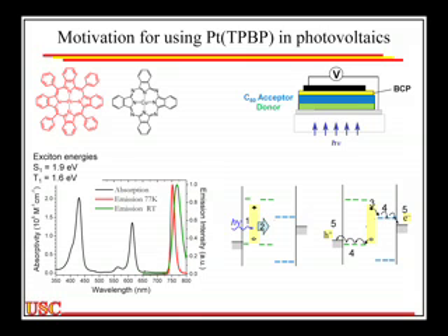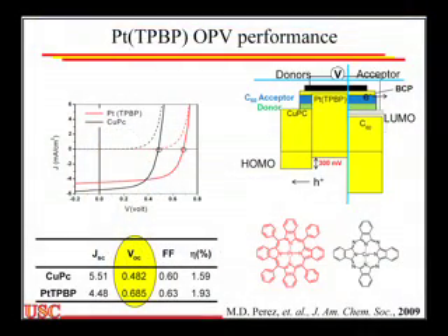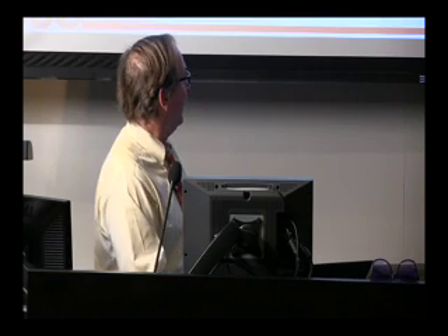The other problems that come up are the carrier conductivity must be high. This is something organics are terrible at, and that impacts the fill factor, so how steep or how much like a hockey stick the curve looks has to do with the conductivity. And we typically solve this by keeping the films thin, but remember, if I keep the films thin, I don't get much light collection, so that's a bit of a problem. And the open circuit voltages are typically low, and I'll talk a little bit about that in my talk, but most of what I want to talk about is going to relate to these first two.